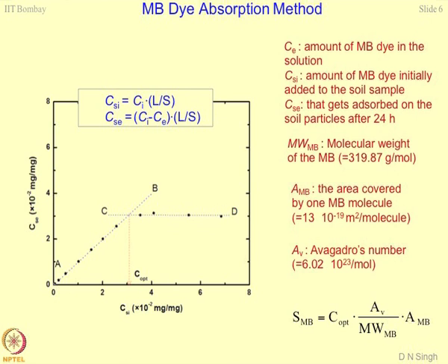So, if you know the C optimum value, and if you know the Avogadro's number, which is 6.02 × 10^23 numbers per mole, divided by MWB, the molecular weight of the methylene blue, multiplied by AMB. So, AMB happens to be the area which is covered by the MB for forming a monolayer. So, the first layer, the coating which gets on the surface, this much area the MB will exhibit. Now, these are the standard values. So, these are the standards which I have normally used for this method. So, then you can get SMB. So, SMB corresponds to surface area which you are getting from the methylene blue method.